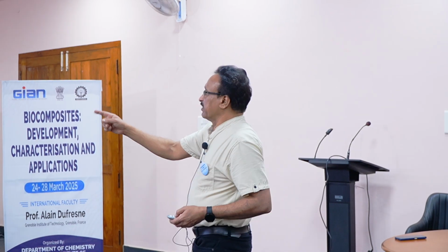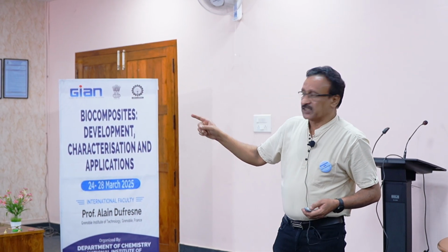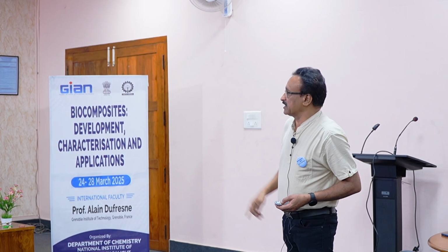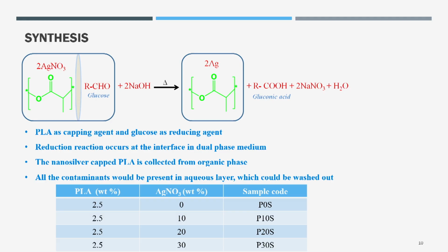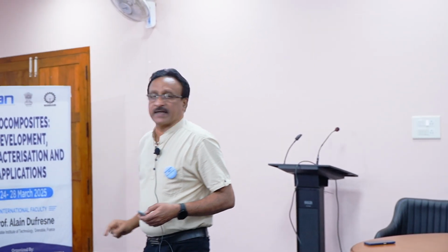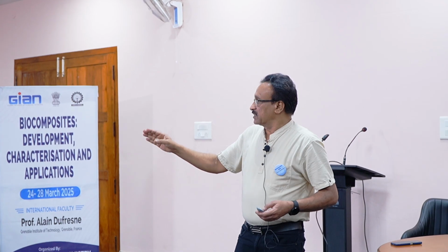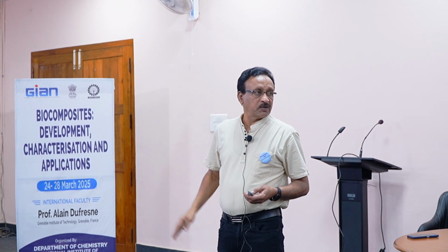And we have made different compositions of PLA. The first column is PLA, the second column is the amount of silver nitrate. Silver nitrate dissociation is quantitative: AgNO3 gives Ag+ and NO3-. So the ratio is 1:1:1. Therefore, whatever molar ratio of AgNO3 is taken, that is the molar composition of silver also. The first one contains no silver nitrate, which is written as P0S. The second one contains 10% silver nitrate and is called P10S, because 10 indicates the percentage of silver.